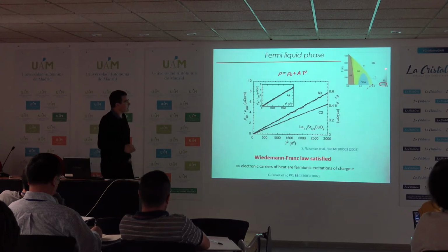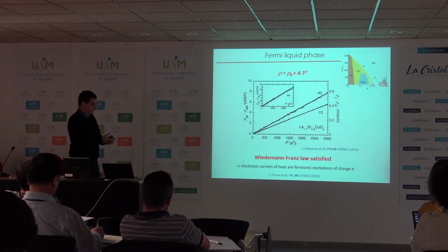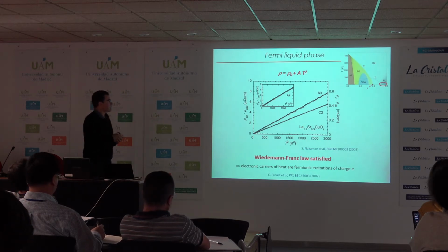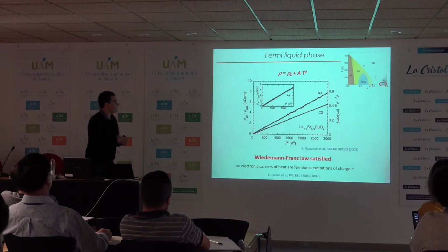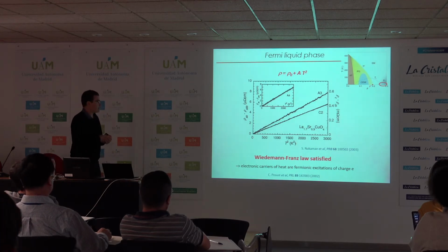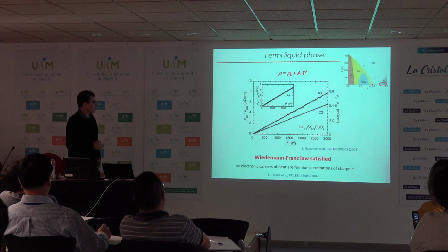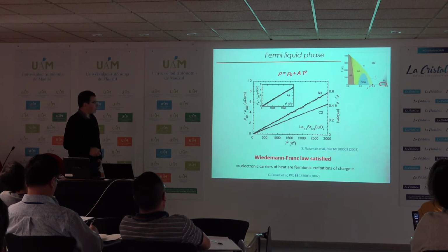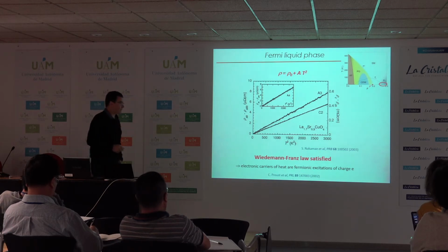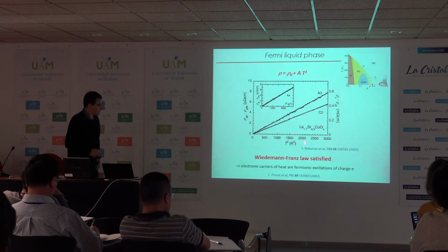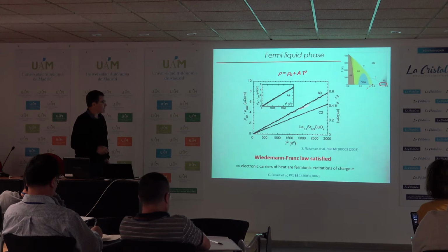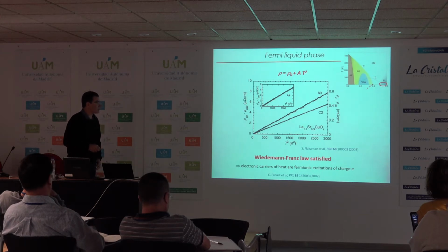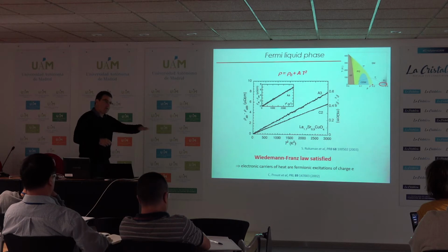So let me start with the Fermi liquid phase, the well-known one where things are rather conventional. This has been discussed, I believe, by Tony at the beginning of this school. Here I show you the resistivity versus temperature for a strongly overdoped non-superconducting LSCO, plotted versus T squared. You see that the resistivity is beautifully T squared down to very low temperature, both in the plane and interplane direction.